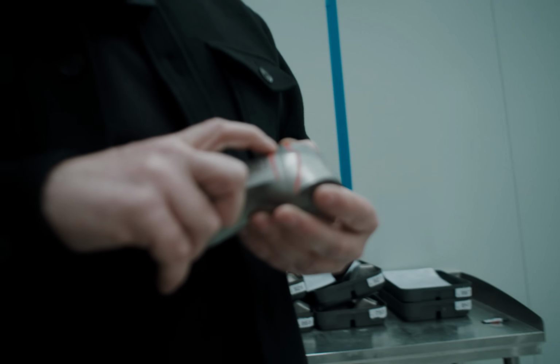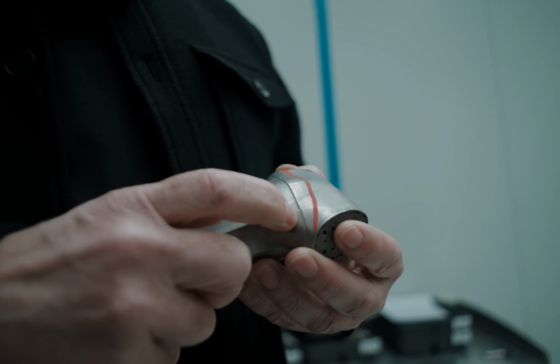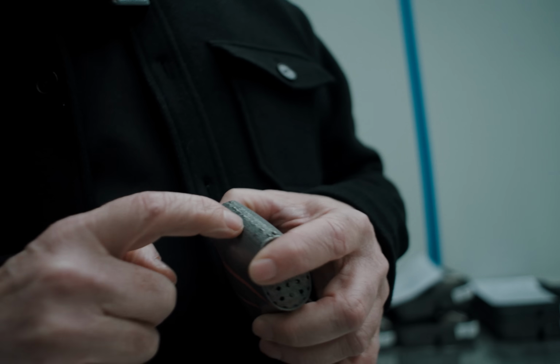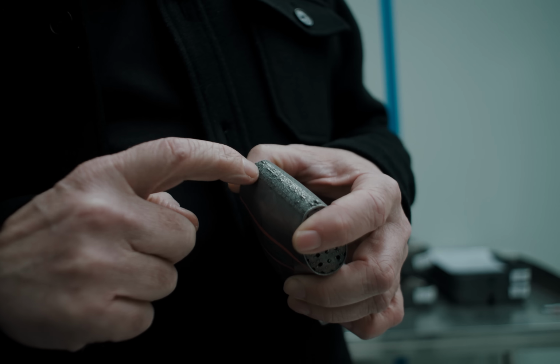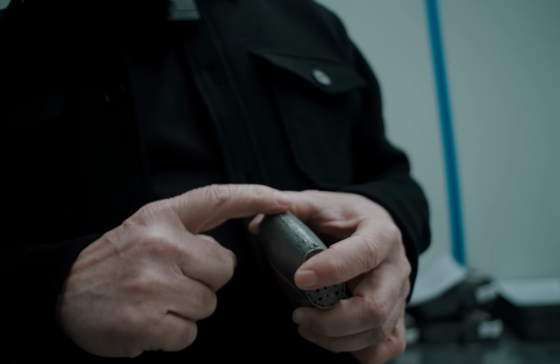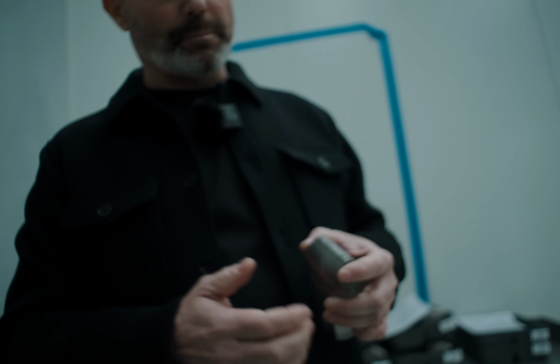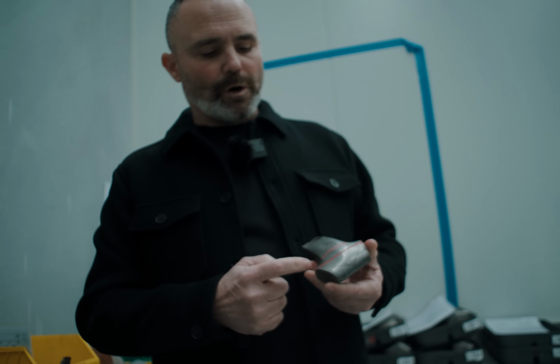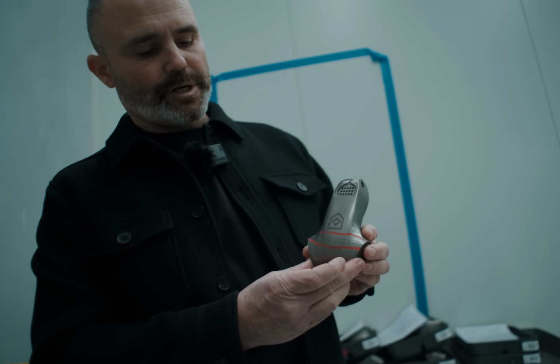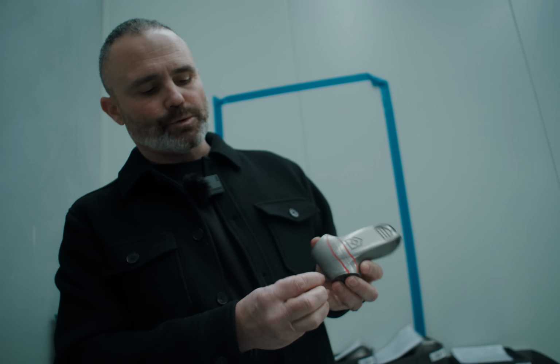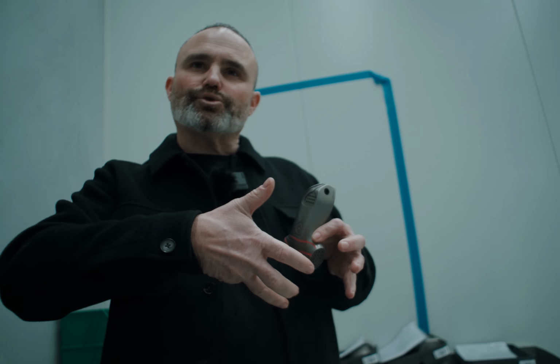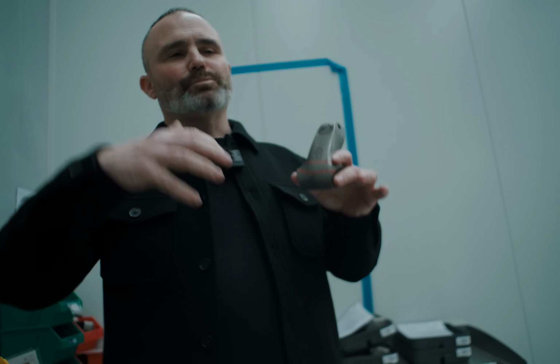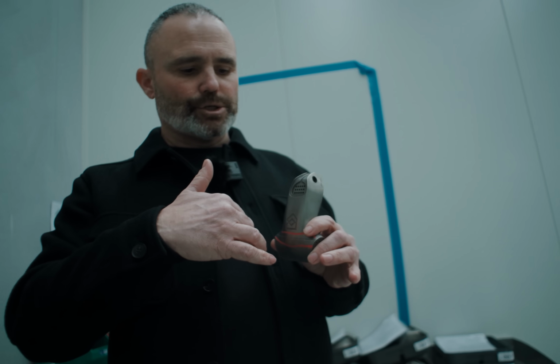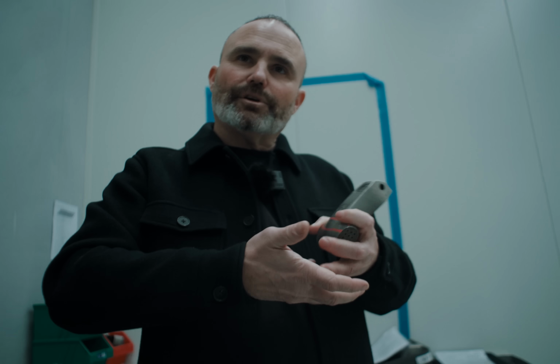That's what we call a shift line. So what would have happened in this print, you can see where the support material was holding it down to the plate. That's where that rough surface is. We haven't linished that off because we're throwing the part away. But what would have happened is at some point during that print, some of these would have let go from the residual stress, you know, we're melting it at over 1,000 degrees. It's putting a lot of heat into a certain part. And then as it's cooling, that's trying to lift and contract.